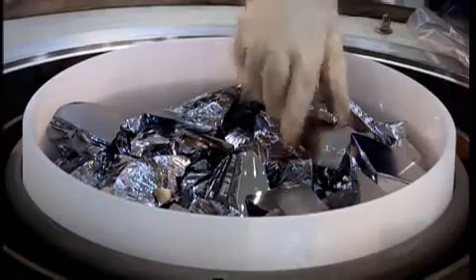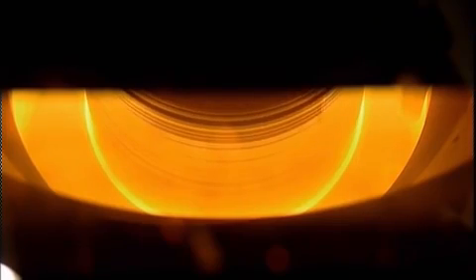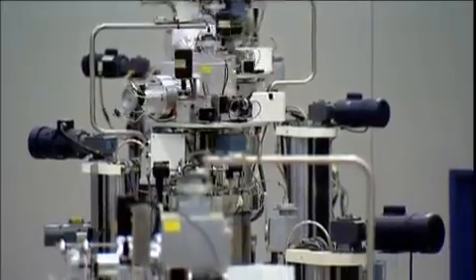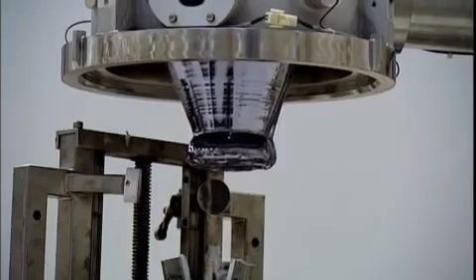They begin with raw polysilicon, or poly, and heat it to 1420 degrees Celsius inside a special sealed furnace, which has been purged with argon gas to eliminate any air. The resulting lake of molten silicon is then spun in a crucible, and a silicon seed crystal, roughly the size and shape of a pencil, is lowered into it while spinning in the opposite direction. As the molten polysilicon is allowed to cool, the seed crystal is slowly withdrawn at around 1.5 millimeters a minute. The result is a single silicon crystal weighing around 200 kilos and with a diameter of around 200 millimeters.